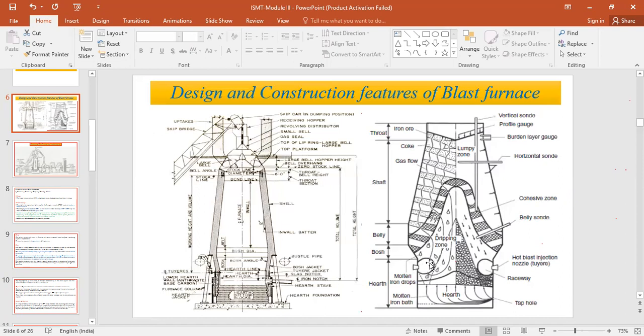And in this way, whatever the reducing gas is formed as CO2 is not stable at high temperatures, so it readily reacts again with carbon and forms carbon monoxide, and that is the gas which travels up and interacts with the solid which is present at the top of the blast furnace, especially in the stack part.